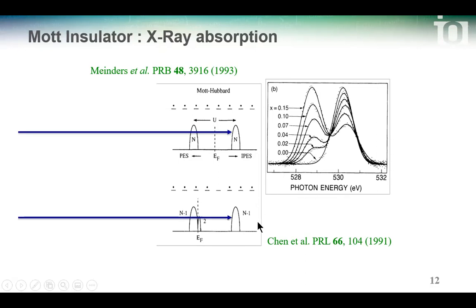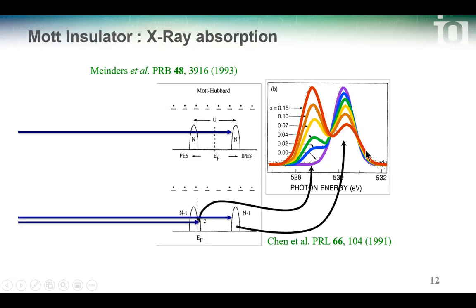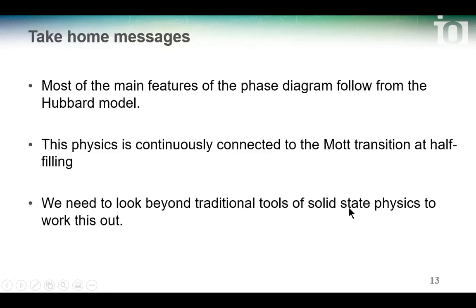Now, suppose you dope, then this peak has to reduce in intensity. You see, if you dope, then the peak has gone down a little bit. And then this one here has gained intensity because you have states now that are available very near the Fermi level. So this is what happens as you dope. And you see that this one goes about twice as fast as the other one decreases. So it's quite convincing that this is a Mott insulator.